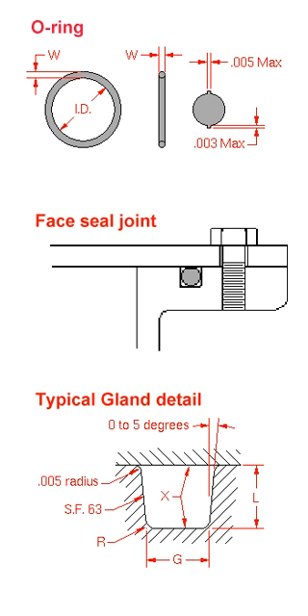There are a few common reasons for O-ring failure. 1. Installation damage: caused by improper installation of the O-ring. 2. Spiral failure: found on long-stroke piston seals and, to a lesser degree, on rod seals. The seal gets hung up at one point on its diameter against the cylinder wall and slides and rolls at the same time. This twists the O-ring as the sealed device is cycled and finally causes a series of deep spiral cuts typically at a 45-degree angle on the surface of the seal.